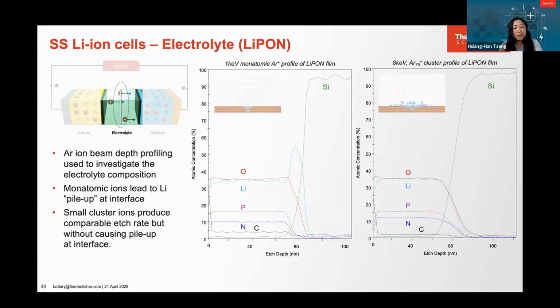And because of this, people moved on and tried to develop argon cluster ion sources, using clusters rather than individual ions to bring a gentler effect, in the hope that we can solve this problem. And it is true that this method has been quite successful and works well for a range of materials, including polymers.